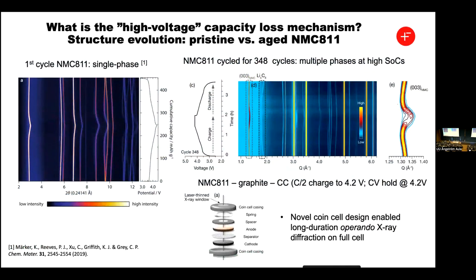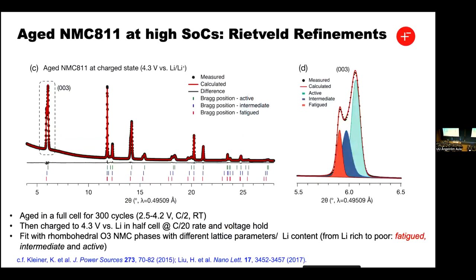So I'm going to go back now and talk about the work of Chao Chu, who, using this long-duration experiment at Diamond, was able to cycle graphite-NMC full cells for a very long time. What he saw, if we just focus on the 003 peak here, which is the one that measures the collapse of the C layers, is that after multiple cycles it no longer collapsed as much. In fact, it got stuck at the top of the fully expanded regime. To analyze that, he pulled the cell out and rebuilt it with lithium metal. He took it to the top of charge, to 4.3 volts, and showed that it was no longer a single phase. In fact, he could decompose it into three components.